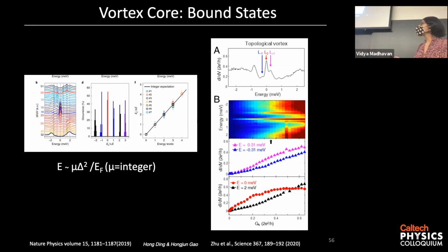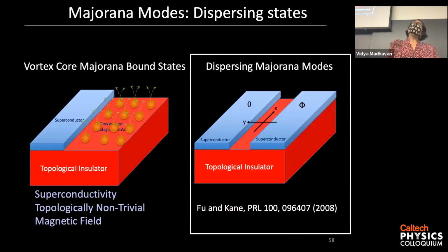So what Hong Ding and his collaborators, Hongjun Gao, showed is that for the Majorana modes, you do find the so-called integer spacing. So the combination of the fact that you have a zero bias peak, which is pretty much at zero within instrument resolution, and the fact that you have integer spacing rather than half integer spacing, these two things strongly suggest that these things might actually be Majorana fermions. Okay. So the next thing to ask is, can you in this very magical system also see evidence for propagating Majorana fermions?